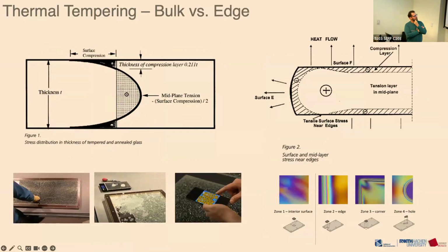The old school way they measure thermal tempering is by a breakage pattern. They take a piece of thermally tempered glass, put a sharp point on it, break it, and then collect and weigh the fragments and see if it's tempered or not tempered. That's the more traditional way to measure the stress profile, and online in a production environment, that tends to be the way it's done, with the operator tuning the pressure and quench pressure to give you the right breakage pattern.